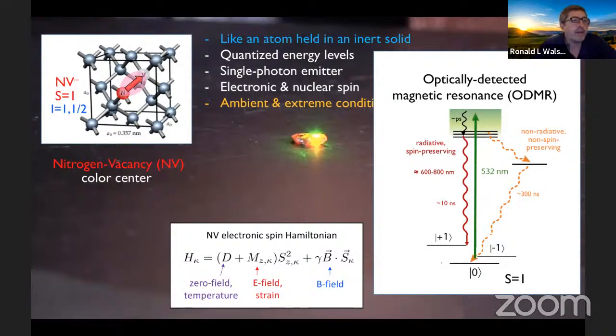And because we're talking about electronic spins that make up the NV, the gyromagnetic ratio of the NV is quite large. It's a Bohr-magneton gyromagnetic ratio, which means that these plus and minus 1 levels shift rapidly with magnetic fields. So small magnetic fields can end up leading to large energy level shifts, which is why the NV can be a good magnetometer.